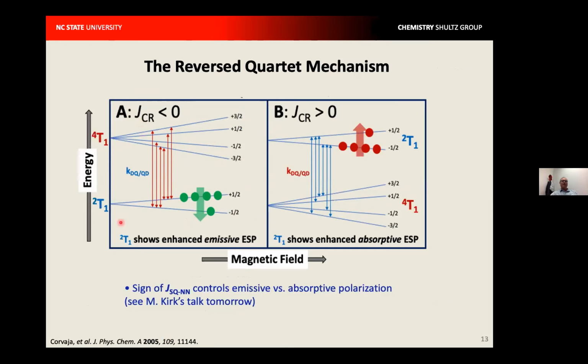So when that is antiferromagnetic, now the trip-doublet lies below the trip-quartet. And spin selective equilibria between the M sub S levels of those two states results in a non-Boltzmann population of, for example, the trip-doublet here, that if you were to do time-resolved EPR on this trip-doublet, you would see an emissive EPR signal. For us, that trip-doublet rapidly decays back down to the ground state with a rate constant that's much faster than the longitudinal relaxation rate constant of the nitronyl nitroxide.